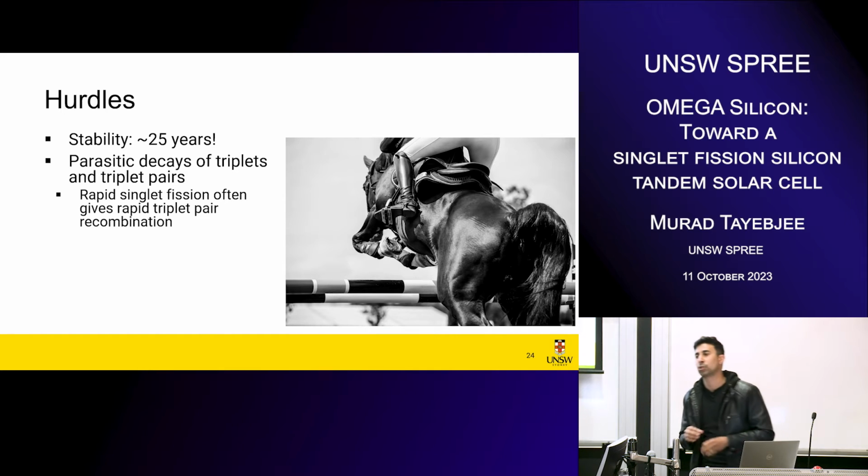So that's going to be a big hurdle for the field. The other thing is this is coming back to those 2 stars that I put on a slide previously, where I said you can have 200% yield of triplets, but for how long? All right, so these triplets don't live forever. We need to get them to an interface, and we need to get them out. If you produce a singlet fission event and your 2 triplets stay together, they'll actually decay much faster than if you manage to separate them. So separating that triplet pair is a big deal as well.